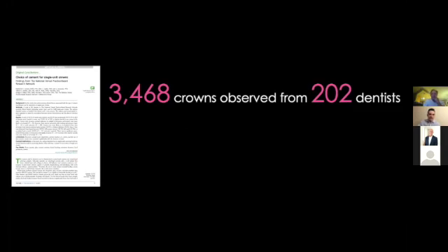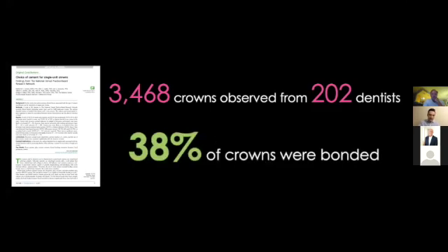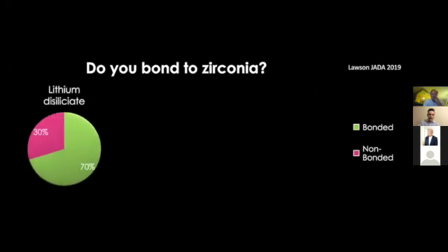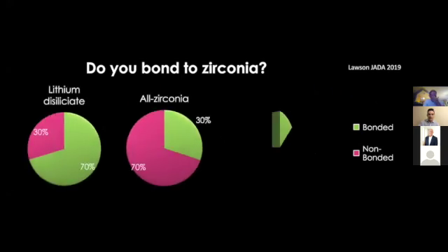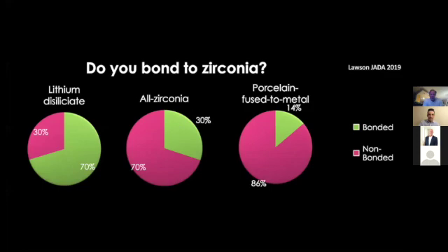This was, I think, the study that I was referring to earlier. It was about 3,500 crowns we observed from 202 dentists, and we found that 38% of their crowns were bonded, but most of those were lithium disilicate. And if we looked at zirconia, only 30% of the zirconia crowns were bonded. I always wondered, why was that number so low? I guess it does make sense because zirconia is so strong that you don't need to bond it most of the time.